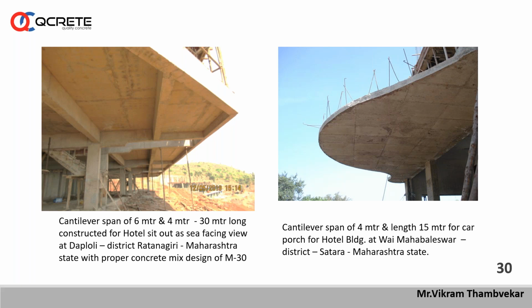So to avoid the effect of flaky material, and to get a good cohesive material and good strength of concrete, we used a better mix design. After analyzing all this material in our laboratory, we gave the mix design in such a way that we got a very good strength as well as a good finish. So mix design is also a very important factor while producing fresh concrete.